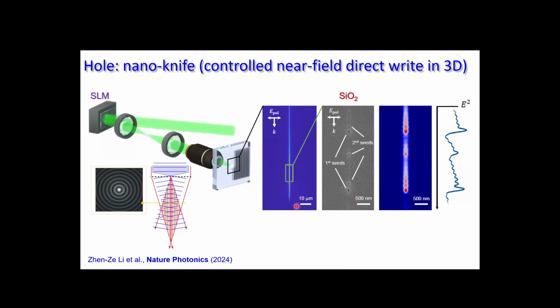So can we do something in the volume? You saw that we can ablate a void in the volume, so it looks like we can drag this void and write a structure inside, but this would be a little bit tricky, and the voids we see with these explosions are very large. And to find single voids inside the volume of your sample is always challenging. So we tend to use Bessel-like beams on a spatial light modulator. This is a Bessel beam kind of cartoon. So you have all the intensity on the axis, and those rings are delivering light to the center along the propagation of your light.